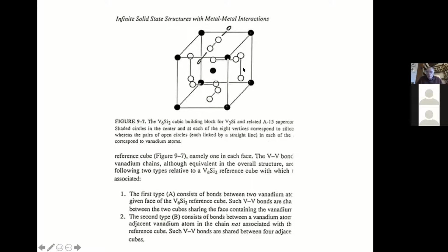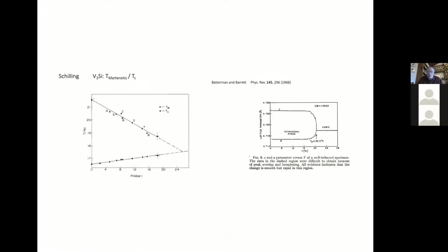So here's just a picture of this A15 structure. You have these chains, say for instance in V3Si, three linear, mutually perpendicular linear chains of vanadiums, and these with a body-centered cubic arrangement of the silicon. What happens when you cool down, it was discovered by Batterman and Barrett, is that you get a tetragonal distortion below TC at low temperatures, where one of the chains expands and one of the other chains contracts, so it's sort of spirals between chains, if you will.